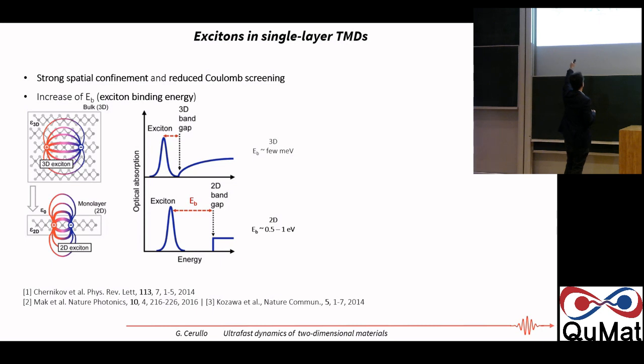So the binding energy of these excitons is extremely low. It's on the order of maybe a few milli-electron volts. So this means that at room temperature, the excitons do not exist. Unless you go to really low temperature, you don't see excitons, but you just see free carriers. Now here, when you go to a 2D material, you have two effects. First of all, you have a quantum confinement. Now you are confining the material in thickness. And then if you look now at the field lines of the excitons, you see that most of them are lying outside the material because it is so extremely thin.